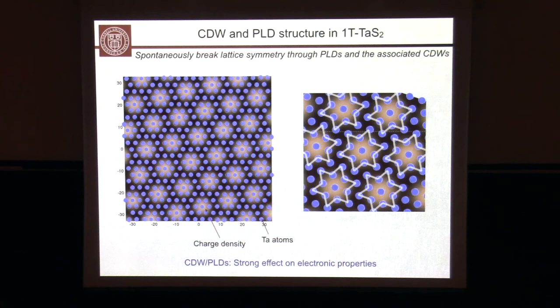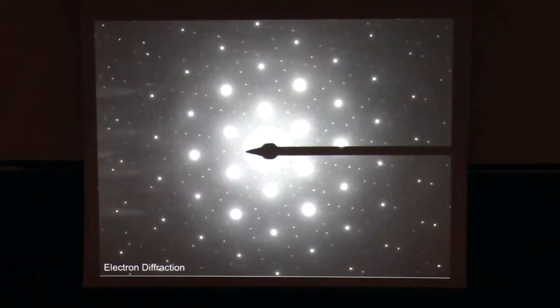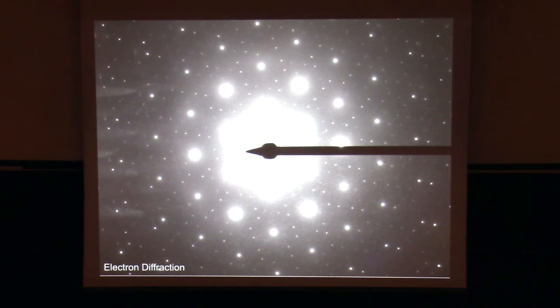So historically, the way it's been done, or an easy way of tracking it, is using diffraction techniques, or reciprocal space measurement. And so I've boosted up the contrast dramatically here. These are Bragg spots of the crystal. But what you see throughout the diffraction pattern is these small peaks. And these small peaks are due to the superstructure that shows you the symmetry breaking and the additional order in the system as the material goes into a charge ordered state or charge density wave state.